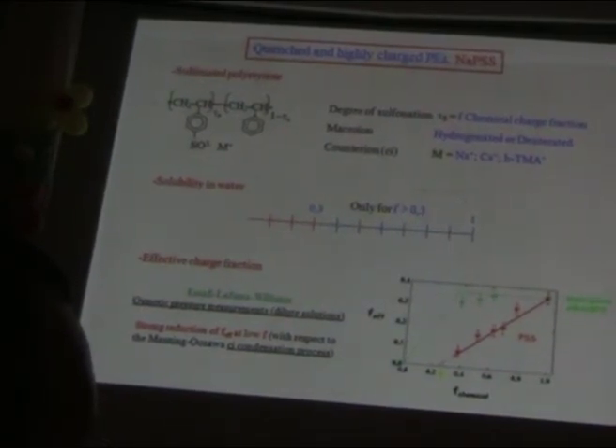So if you vary the degree of sulfonation, of course, at low degree of sulfonation, up to 30%, the polyelectrolyte is insoluble and is perfectly soluble after. But of course, it is only hydrophilic when you have 100% sulfonation degree. If you reduce this sulfonation degree, you introduce some hydrophobic effect. So it is an example of a hydrophobic polyelectrolyte, a quenched one, provided the sulfonation degree is less than 1. Okay? It is important because you also have annealed polyelectrolytes.